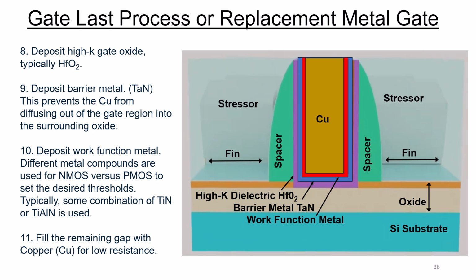Step number 8 is to deposit the high-K gate dielectric. And we're typically talking about something like hafnium dioxide with a pretty high K number. Step number 9 is we deposit a barrier metal, and this is typically tantalum nitride. And that's shown in the blue region here. And this prevents the copper from diffusing out of the gate region into the surrounding oxide. The copper really wants to move, and the tantalum nitride confines it to this space.